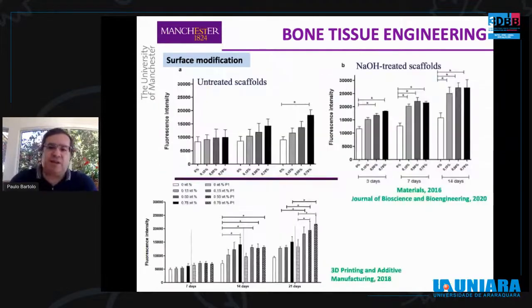We are exploring other technologies. A few years ago, we reported the use of NaOH to treat the scaffolds without compromising the mechanical properties. And our initial results show a positive effect on the osteogenic differentiation. This year, we published another paper showing also a positive effect on chondrogenesis. Another strategy was based on coating the scaffolds with P1 protein, extracted from latex from the rubber tree in Brazil. This is a project funded by FAPESP and University of Manchester, and we obtained very interesting results using this protein, not only in terms of improving cell adhesion, but also the osteogenic differentiation and also angiogenesis.